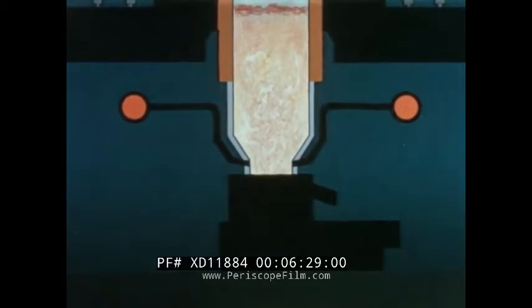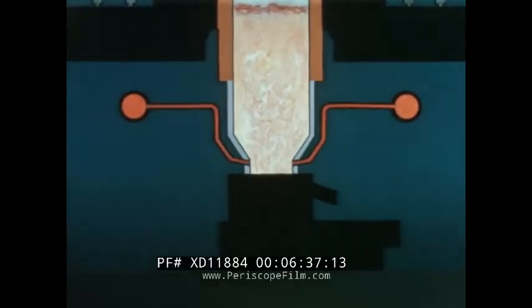Air, preheated by blast furnace gas to 750 degrees centigrade, is used for smelting. The heated air is blown into the furnace shaft through water-cooled tuyeres. In the blast furnace, the combustion of coke produces a gas mixture rich in carbon monoxide, which, as it passes upward through the charge, reduces the zinc and lead oxides contained in the lump sinter to zinc vapor and liquid lead.